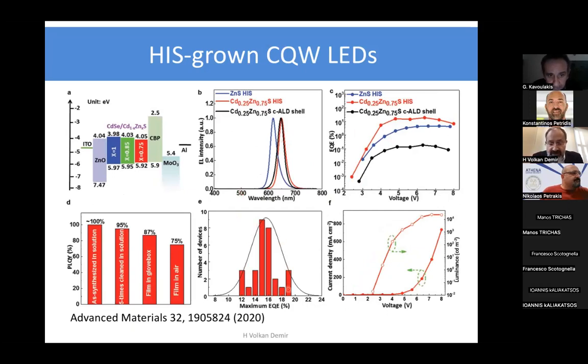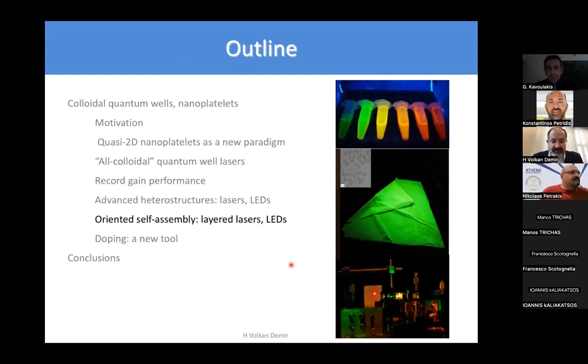Here you can see histogram of the devices we make. This is the hero device. I told you about several of them, 3 of them here, but the distribution is there. And actually on the average, we can achieve a value around 15%. But this number, hero device, considering 20% is theoretically the maximum possible value, puts this type of colloidal quantum well-based LEDs on par with those LEDs we make using colloidal quantum dots. Obviously, dots, our group and many other groups worldwide have been working for a very long time to achieve highest efficiencies. And with this type of engineered colloidal quantum wells, we were able to get the same level of performance.